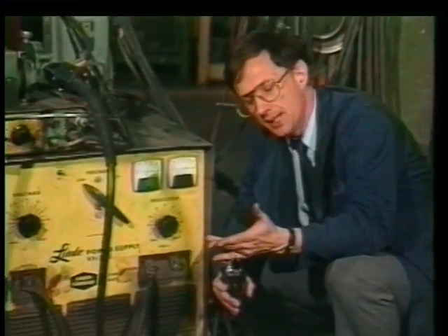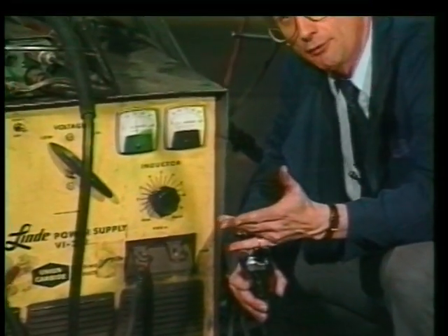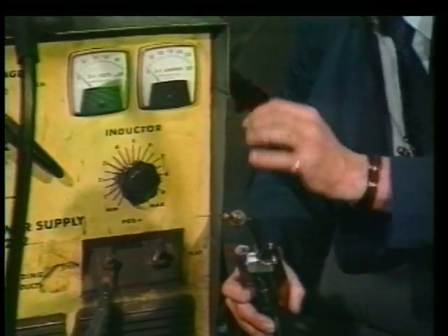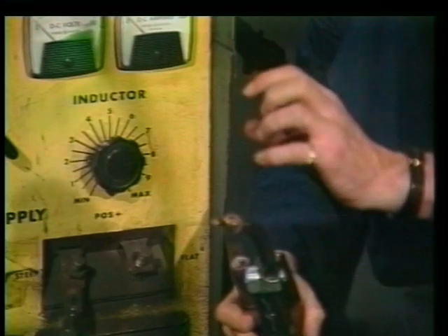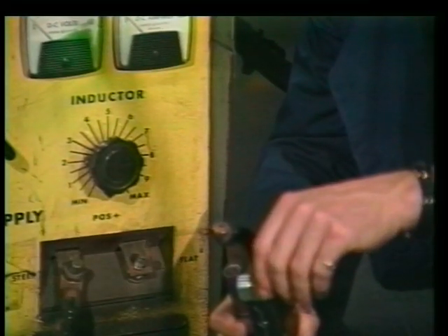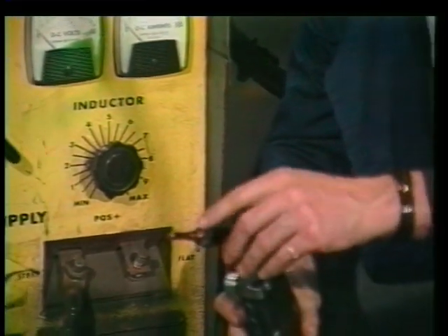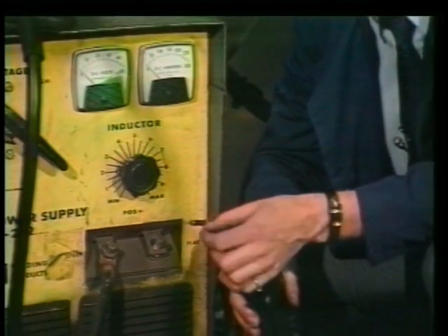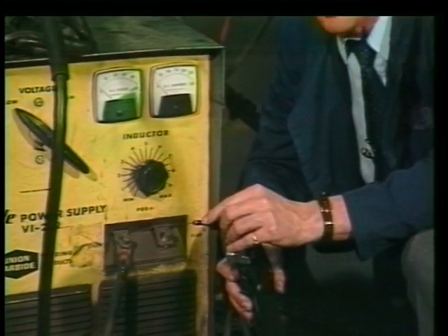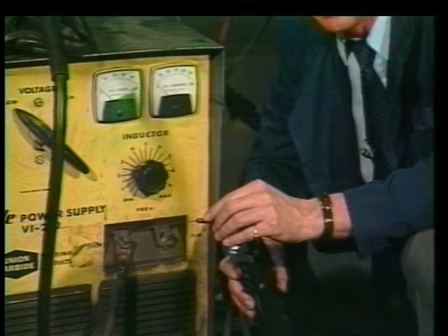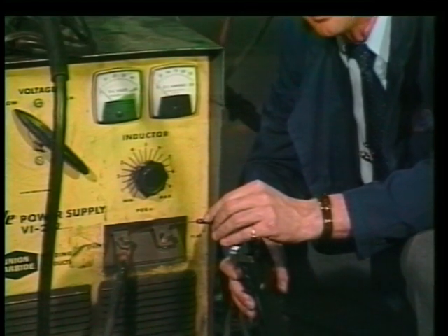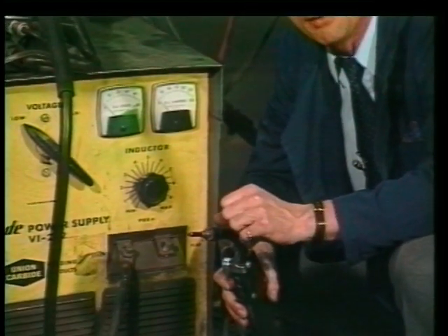The faster that the wire is fed through the torch, then the more amperage or current it can draw from the power source. Now you got to remember that the current actually is fed into the wire just about a quarter of an inch from the end of the contact tip. So it hasn't got far to travel.